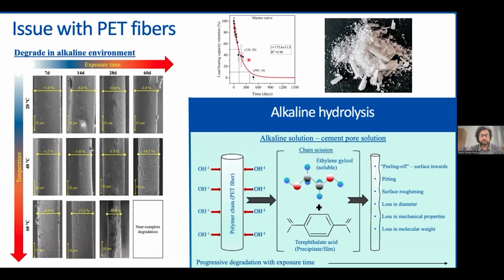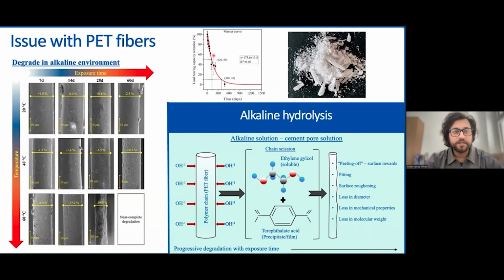Now, what we also did, using the Arrhenius degradation law, was try to model the effect of this degradation on the load-bearing capacity of these single fibers. And the model revealed very alarming results. Here you see that after these different aging processes, the prediction suggested that PET could lose half of its load-bearing capacity within 120 days, which is the point here. And it can lose 90% of its load-bearing capacity within a little over a year, which is the point here.